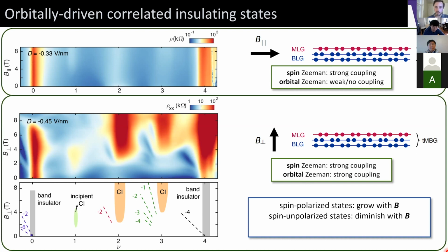Now, the curiosity here is that if these states at zero field were spin polarized, then we would expect the energy gaps to grow with magnetic field in either direction, since either direction of the field would couple to the Zeeman term and grow the spin gap. And in contrast, if these were spin unpolarized states, then we would expect that they should diminish with magnetic field in either dimension, since we would be closing this spin gap by applying larger fields. But neither of these is what happens.